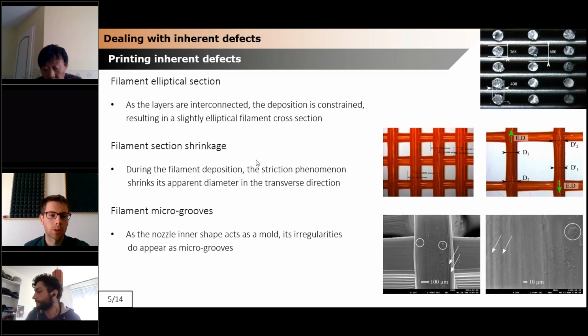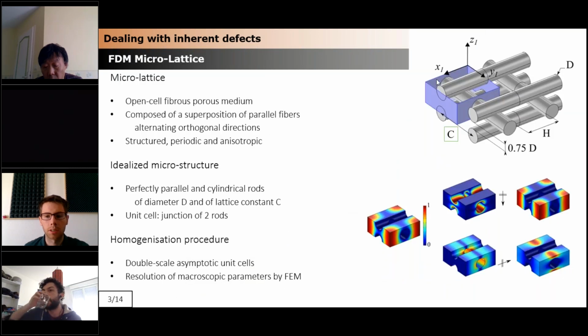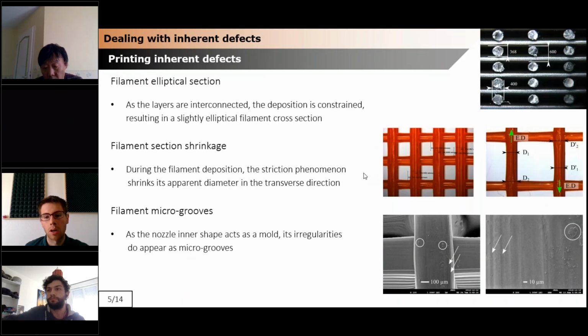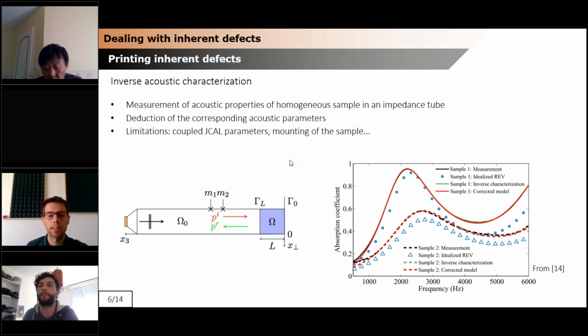So exactly, to account for these defects, either you can change the unit cell to account for them, or what you can do is directly do the work experimentally. So we can use inverse acoustic characterization to retrieve the intrinsic acoustic parameters of an homogeneous sample. So basically, you put an homogeneous sample in an impedance tube, and with some method, you can come back to the acoustic intrinsic parameters.